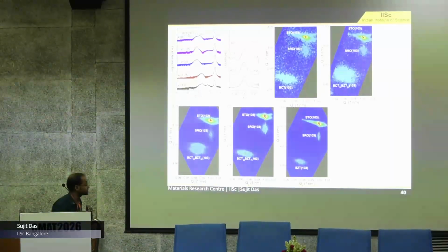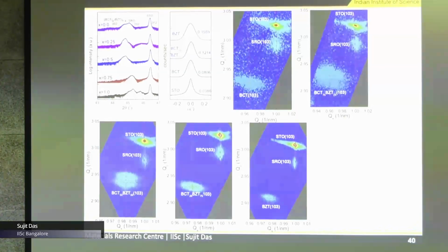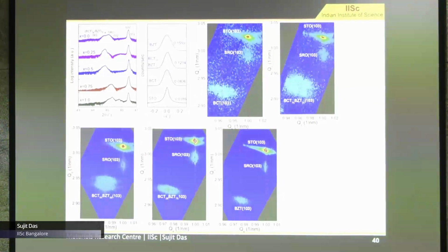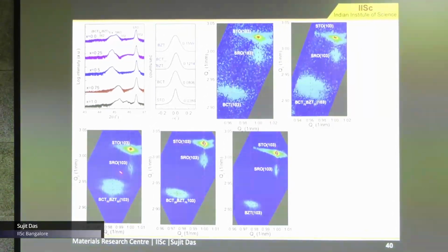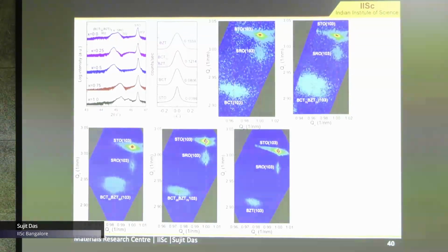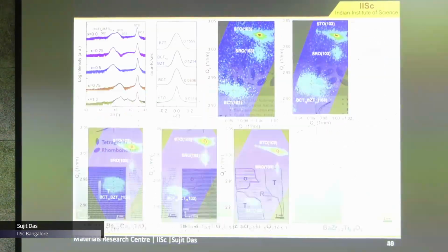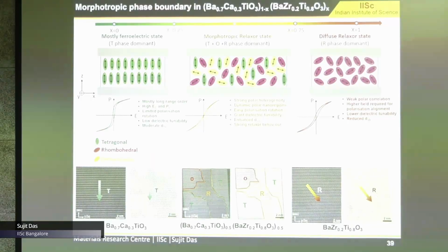And then we checked the structural study, again the single crystalline phases, and the full width at half maximum from the rocking curve is small, that means the film quality is also pretty good. And we checked the reciprocal space map, we found that they are all relaxed, particularly the 50-50% has a peak splitting, that means it has a mixture of different phases. So that we can also confirm from the TEM.